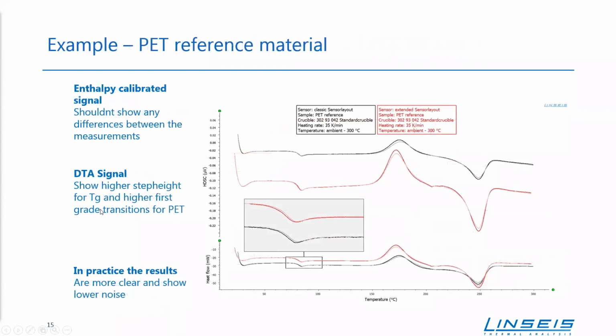But yeah, as you know, not everything is made of metal. So for a more realistic sample, we use also a well-known sample, our LINSEIS PET reference material. And yeah, so at first we will have a look again at the DTA signal you can see in the top of the screen or of the diagram. And there we can see there are some huge differences. So all in all, higher transitions we can see here. And what's important here in this case is the higher Tg, the higher glass transition at around about 80 degrees. So this transition in the DTA signal is much higher. And yeah, so this is exactly what we want to see here.